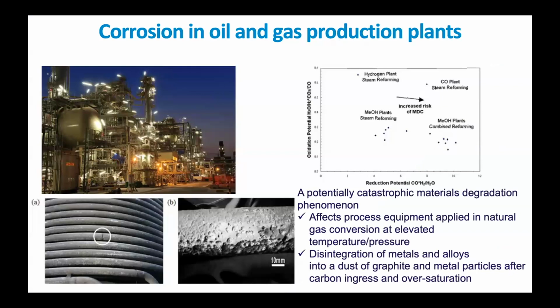Of course, we all like renewable energies, but we cannot deny that we also rely on oil and gas. And so the oil and gas production plants suffer from potential catastrophic materials degradation. These phenomena affect the process equipment applied in natural gas conversion at elevated temperature and pressure, and lead to the disintegration of metals and alloys into, in the case of metal dusting, for example, dust of graphite and metal particles.